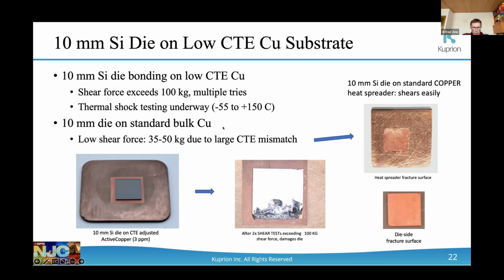But when you put it on a normal bulk copper with a large CTE mismatch, in the best case you get some strength, but often they just pop off when they come out of the oven because of the high thermomechanical stresses between the two. I don't think anybody else can do this. This is really great, and we just did it with a 15 by 15, and everybody wants to get bigger, with the dies going 6 by 6, 10 by 10, and things like that. So this is a must. There's no other way you can solve this challenge.